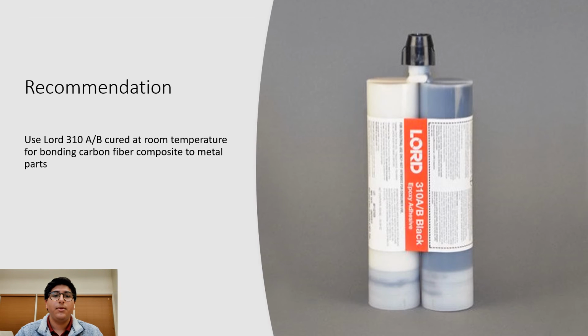Based on the tests done, the ultimate strength of the LORD 310A to B epoxy was determined to be 1,600 psi when cured at room temperature. This was deemed suitable for the team based on the forces that the suspension links and drive axles exhibit throughout driving at competition, which means that the contact area for these will not need to be an exorbitant length that would mitigate the benefits of using a higher strength-to-weight ratio component such as carbon.